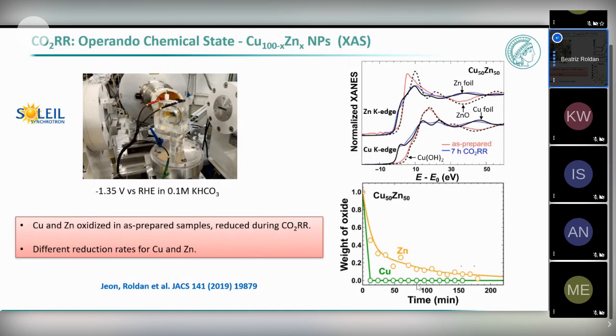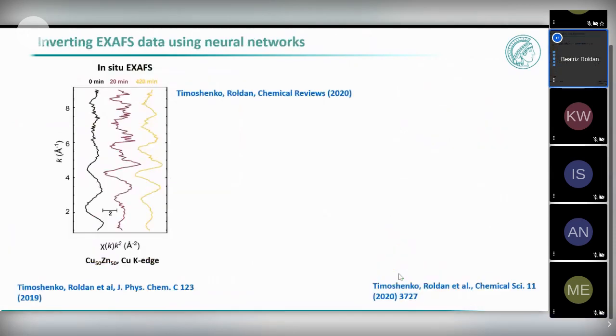So we believe that this is affecting the selectivity, because at the beginning we start having copper oxide in contact with zinc oxide, and then very quickly we have copper in contact with zinc oxide, and then at the end we're going to have copper interacting with zinc, so we make brass. To look at this in more detail, we can measure X-ray absorption spectroscopy.